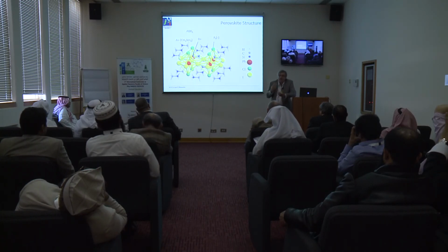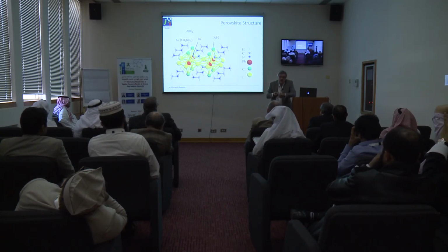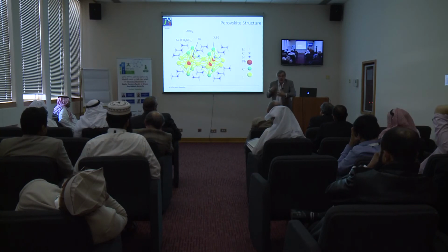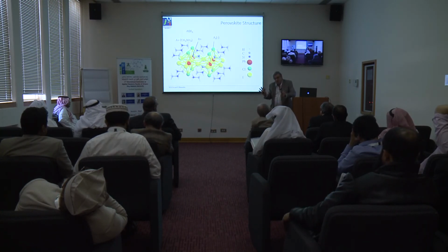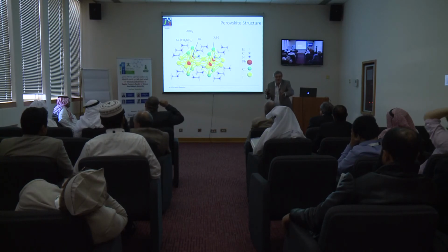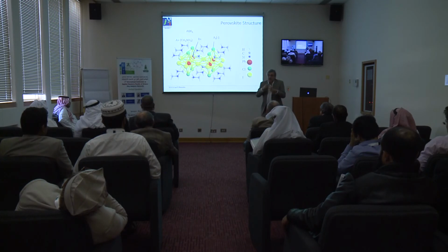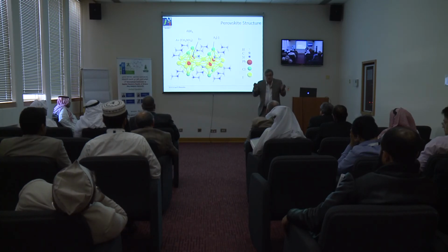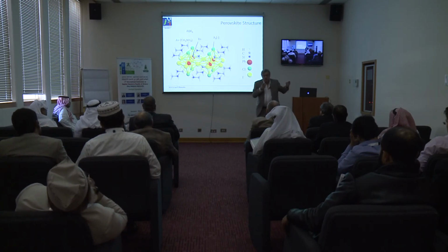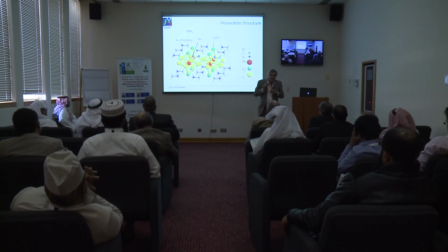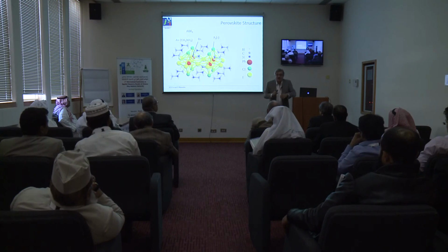So this is called a mixed conductor, because you can move ions like an electrolyte, and it can also move electrons and holes like a semiconductor. So this is the worst thing you can find for characterization. Why? Because you apply a voltage, and you have a lot of possibilities then. You can be moving electrons, or you can be moving ions, and you don't know what you're moving. And it's very difficult to distinguish what you're moving.